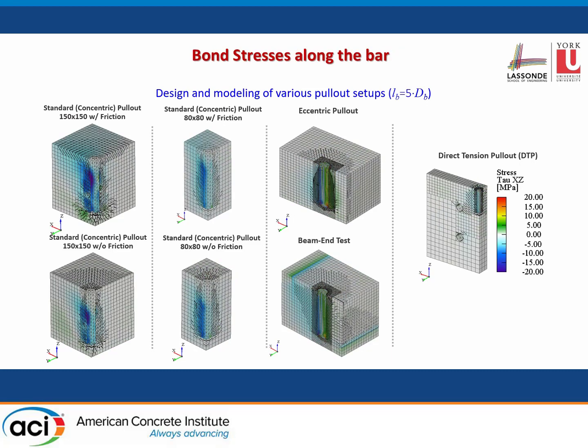And this is a very interesting result because it shows you the distribution of bond stresses along the bar. The most interesting aspect is if you look at the beam end test and the eccentric pullout test, which are second to last in the column, you see a radical change of color, which represents different distribution of bond on the two faces of the bar. So on one face of the bar, you have bond stresses going downwards. On the other face of the bar, you have bond stresses going upwards. So there is a reversal of bond stresses, which confuses the issue completely.